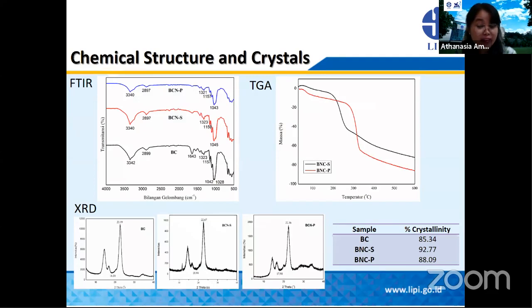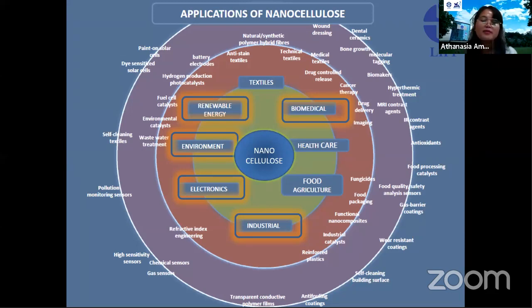Similarly for the bacterial cellulose, using the sulfuric acid hydrolysis, it can also produce higher crystallinity compared to the mild acid hydrolysis. So we have been exploring these two resources from waste-based materials in our surrounding environment. But now we are trying to explore what the applications of those nanocellulose are.